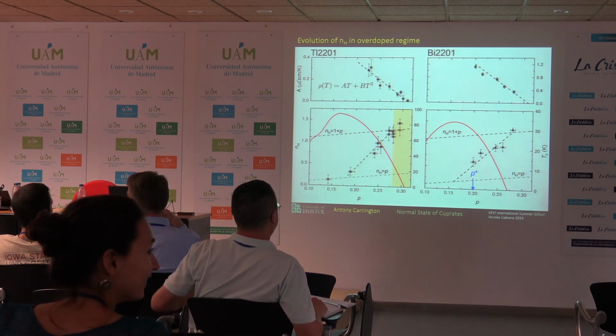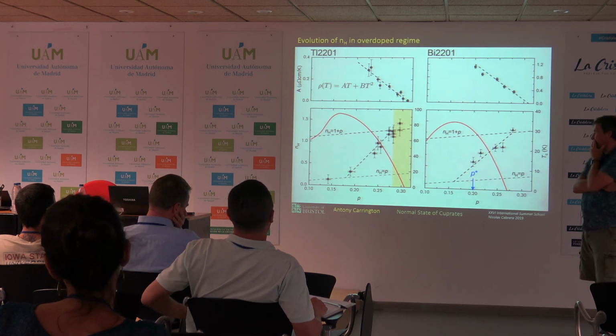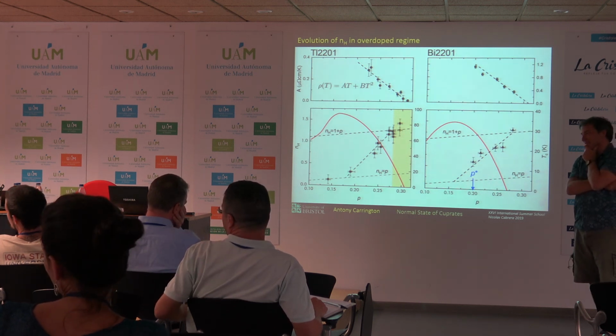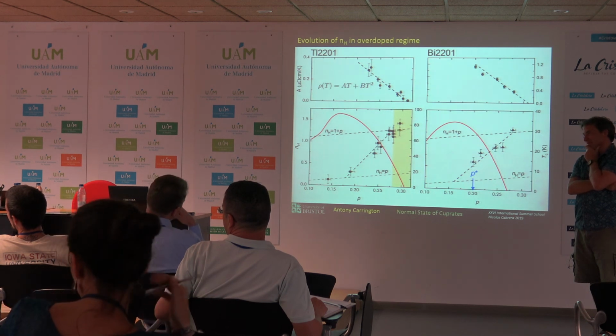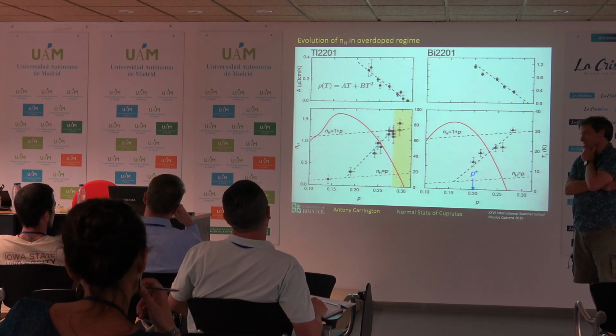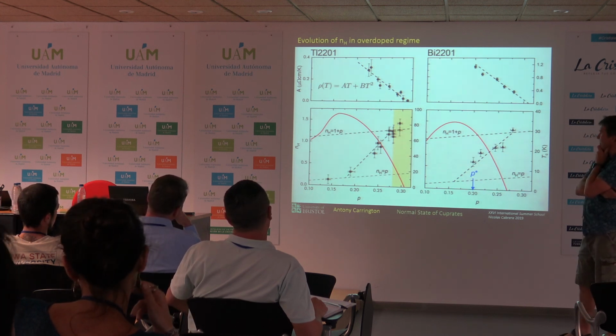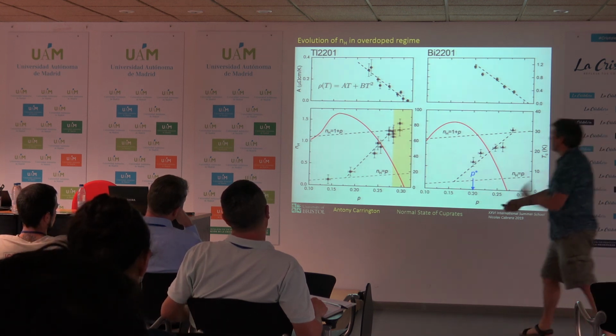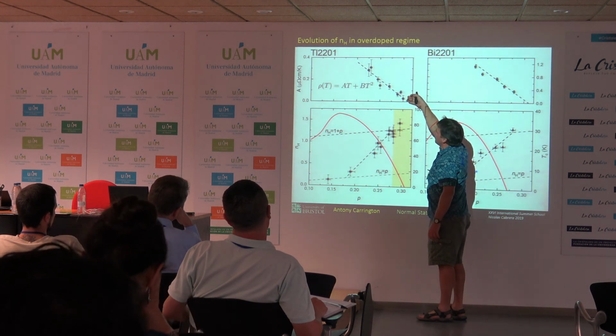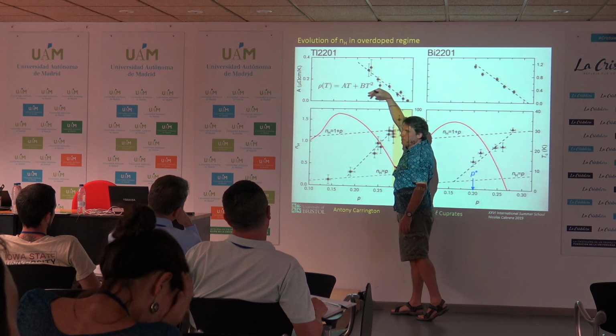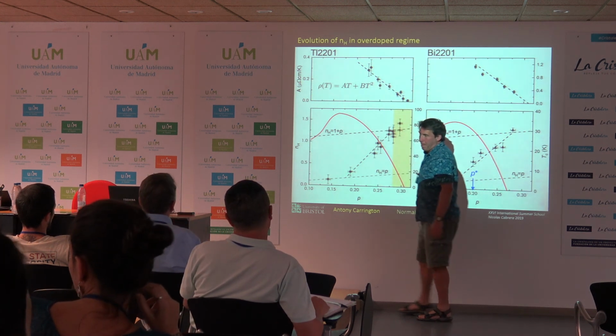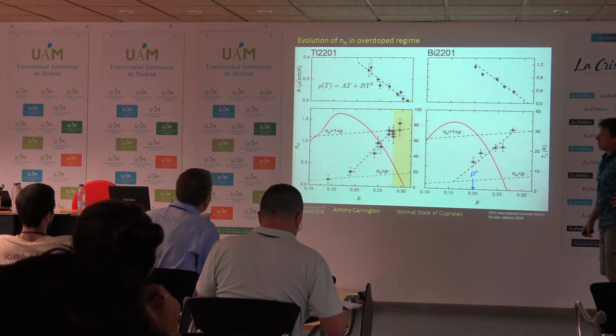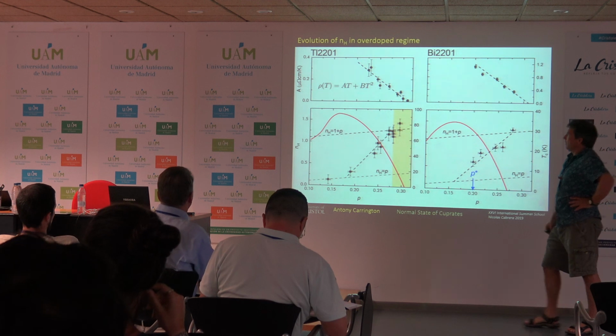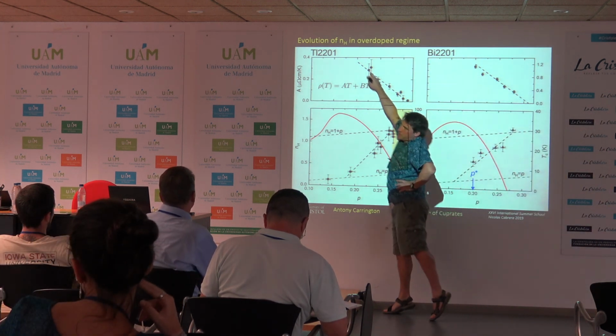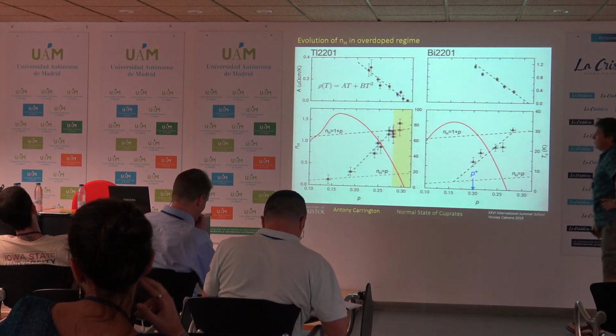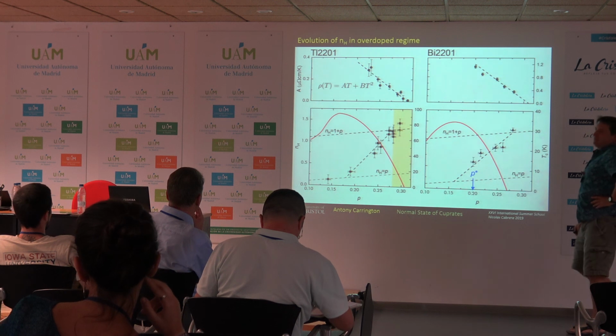I agree. I'd like to understand the plot that you have up here better. So let's discuss what happens to the resistivity exponent, T to the alpha. In the yellow region, where you see 1 plus p, large Fermi surface, quantum oscillations, the resistivity is T squared. So I haven't shown this, but if you were to plot the T squared component, it would be independent of Tc. As soon as you start deviating from the 1 plus p line, the exponent goes from T squared to T, gradually. So you could say that you've got this linear term that's increasing with the T squared, and by the time you hit the line nH equals p, it's basically T. Correct. Okay, so that's about the resistivity.